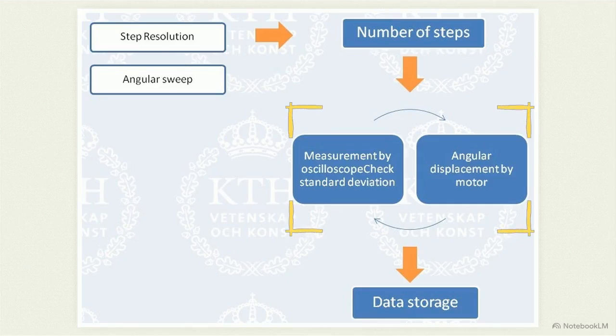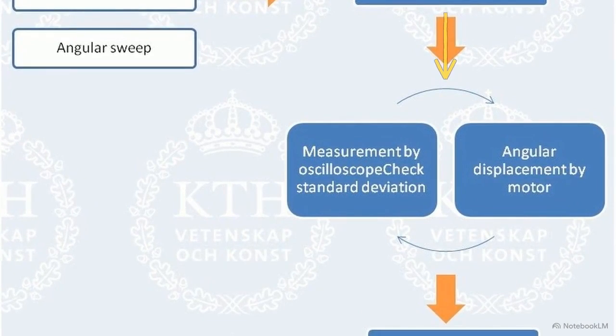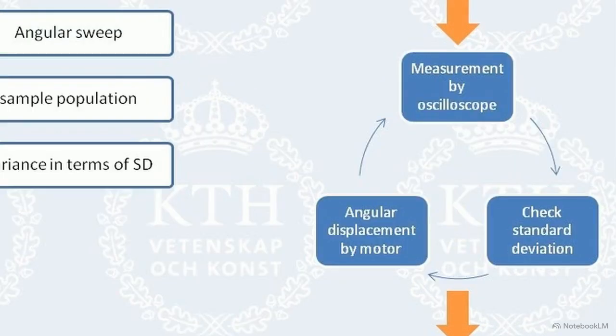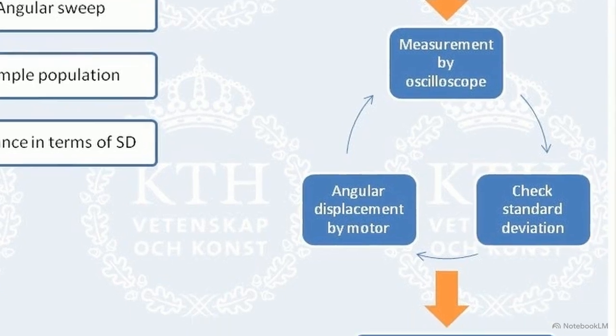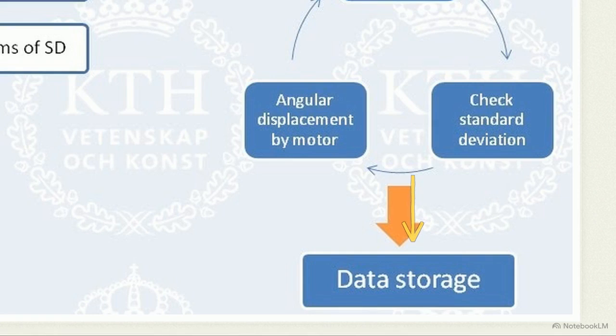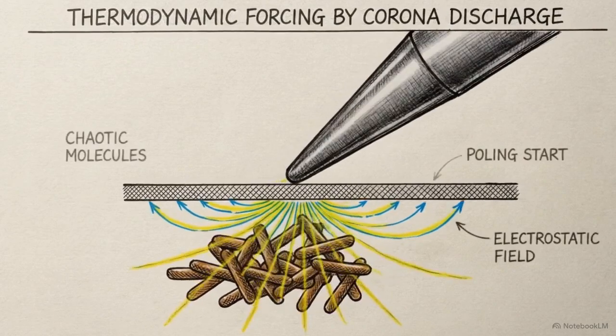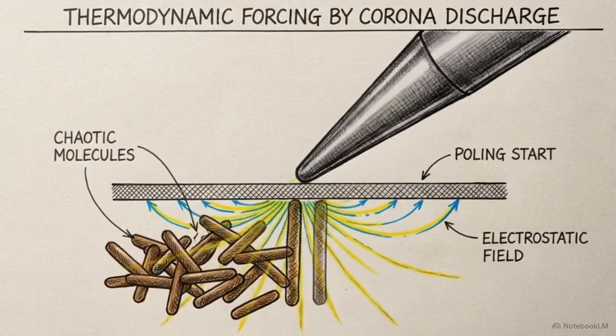This flowchart details the software automation loop that drives the metrology setup. Custom LabVIEW software controls the motor steps while capturing the exact voltage output from the oscilloscope. To ensure accuracy, the software acts as a gatekeeper. It calculates the standard deviation of the measured samples, automatically rejecting unstable phase shifts that lack sufficient modulation before any data is stored. We started with organic chemistry, physically forcing bulk polymers out of their natural centrosymmetry using an intense high-voltage corona poling process. We then translated that molecular alignment into measurable data using Fabry-Perot interferometry and matrix mathematics.